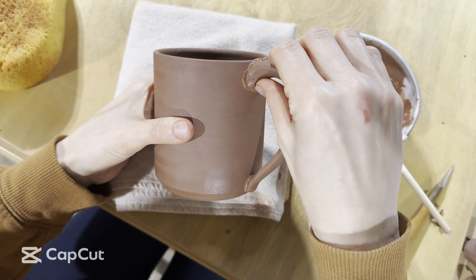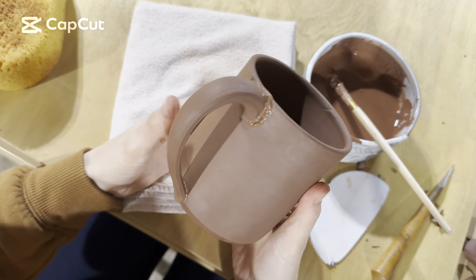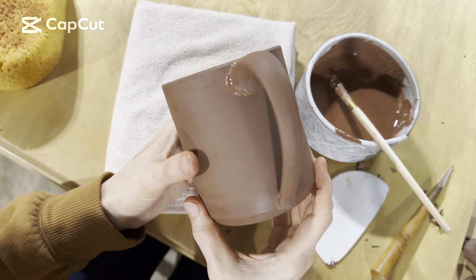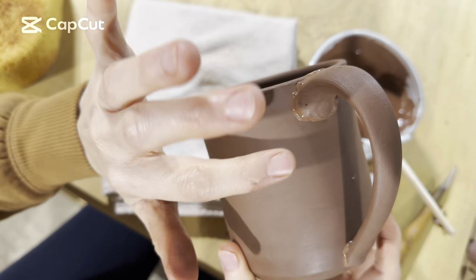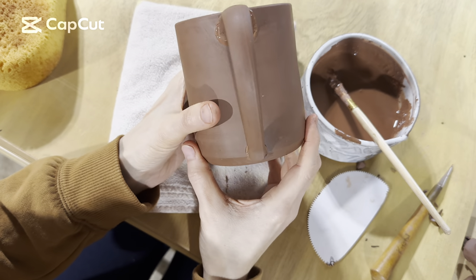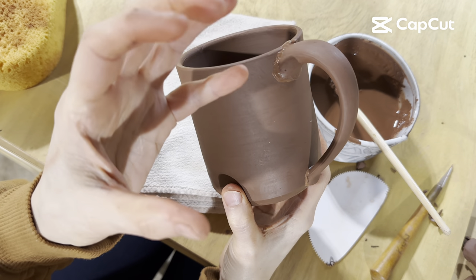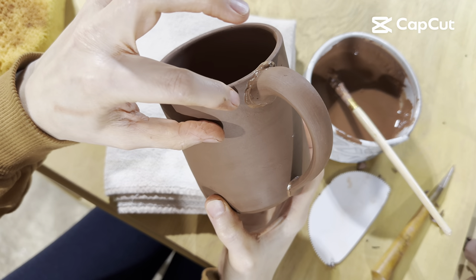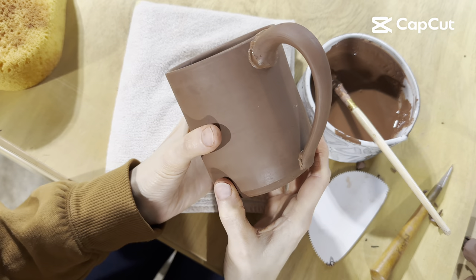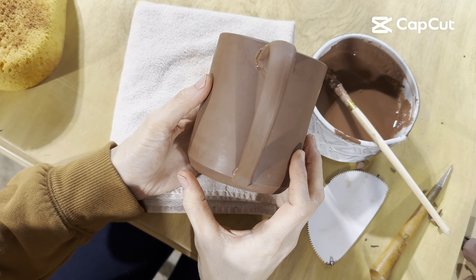Now this is where things are a little bit different than normal. Your instant reaction is going to be to take your finger and swipe this away, clean it up, and start going in there with a metal or wooden tool rubbing it all over the place. Don't do that. Leave this alone. What's going to happen is all of this liquid clay — this slip — is actually going to start to shrink, and as it shrinks it's going to pull into the areas where the cracks normally happen.